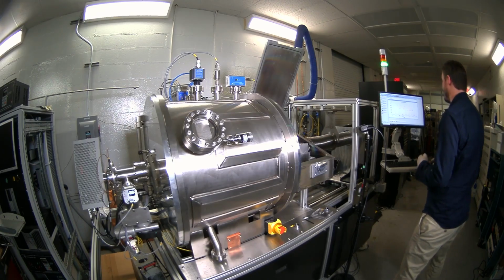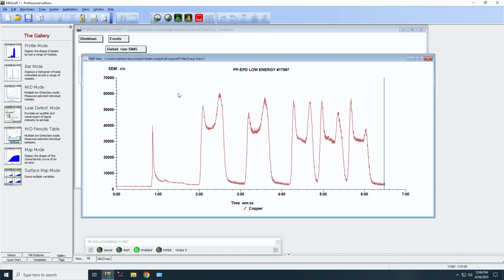Okay, let me go back to the SIMS trace so I can talk about how you would set up automated endpointing. You can see here there are 5 distinct copper peaks for the 5 layers. The way you can define the endpoint is either on rising edges or falling edges, and you can also count layers. So let's say this is M5, 4, 3, 2, 1. I want to end somewhere here in what would be via 3, because I want to image M3 in the SEM. So the way I would do that is to look at falling edges.